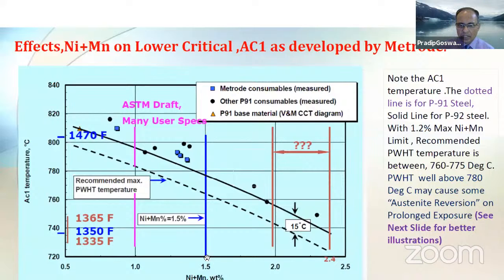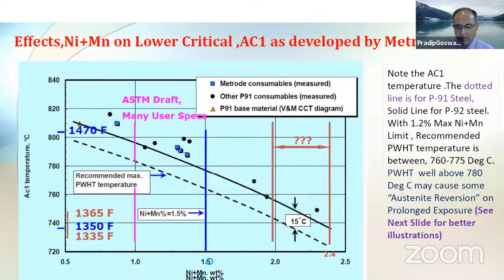So you see here, prior to 2019, the maximum nickel plus manganese allowance for this grade of steel was 1.5%. Based on 1.5% maximum, the AC1 temperature used to be in the range of 760 to 770 degrees centigrade. And that used to be the maximum limit for post-weld heat treatment temperature, which the industries were asked to follow.